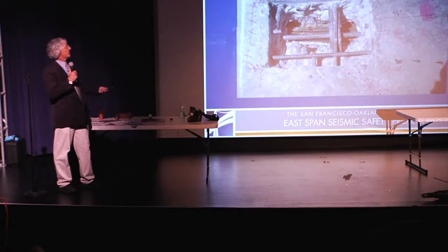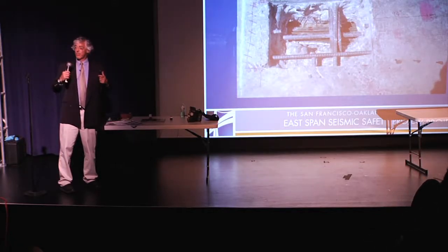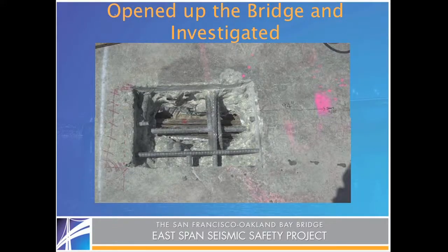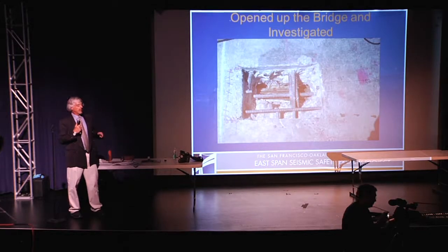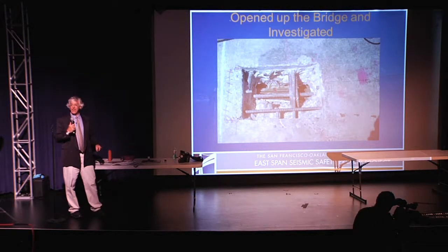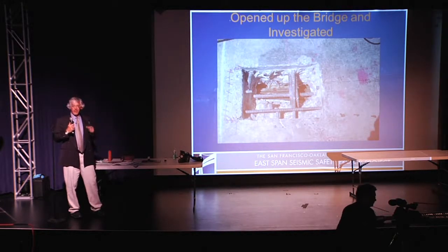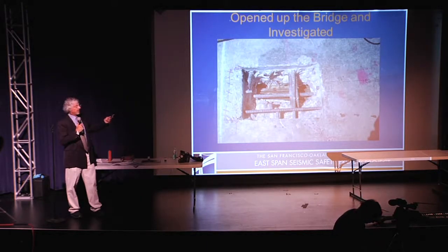Next slide. As soon as we discovered this, the first thing we did was put together a team. We brought together all the elements of a team that we needed to evaluate and figure out exactly what we needed to do. First thing you have to do is get as smart as you possibly can about it. And what we did is we went to areas where we could get access to those. Kind of like if you have a problem with your knee, you're not going to want to open up your whole leg, you just want to open up a little hole. So we went to strategic locations where we knew we could get access to it. Here's a shot of an opening at the top of a deck.